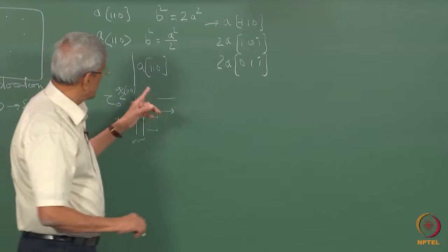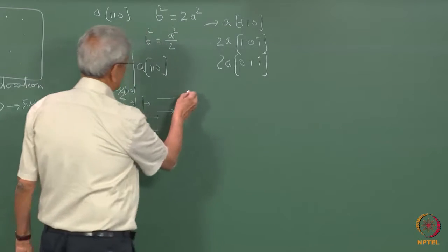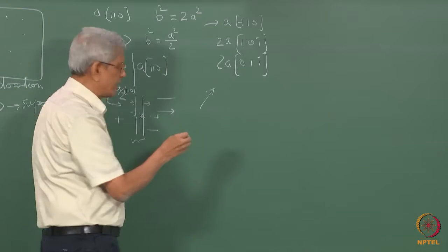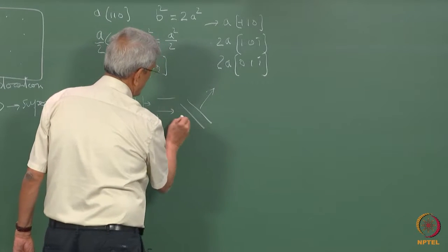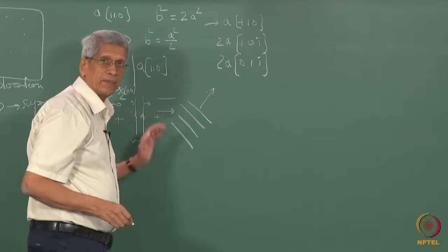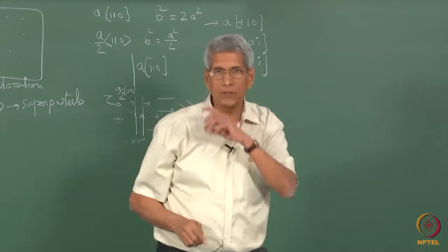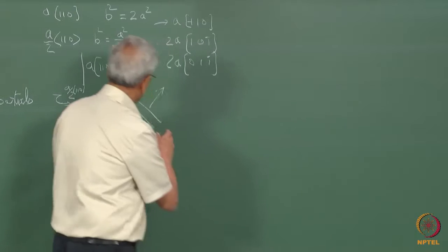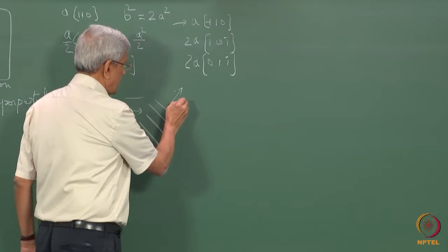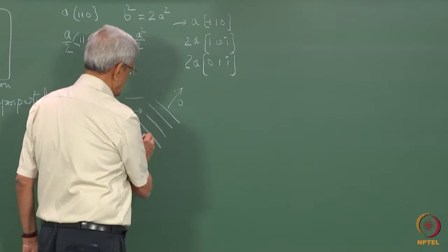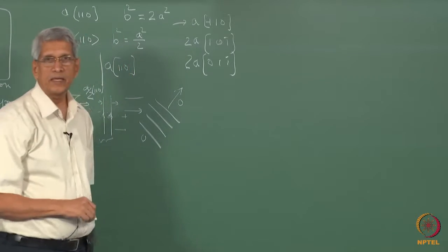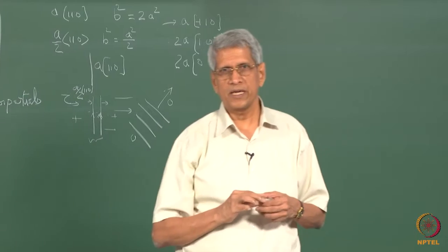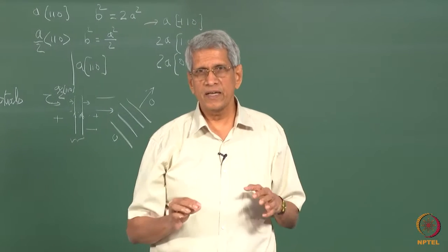Now the same thing, when it has to happen in a direction like this, which is the slip direction, we should have 4 dislocations passing through it. After all the 4 dislocations have passed through it, only then will we find that the ordering is perfect in this region. In between, an antiphase boundary is going to be created. This is clear?